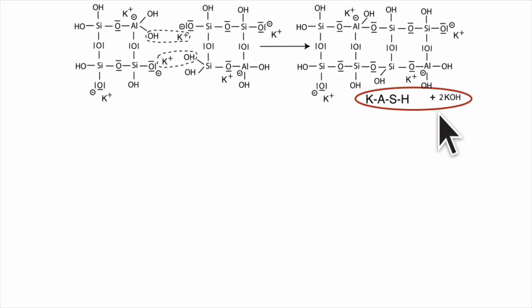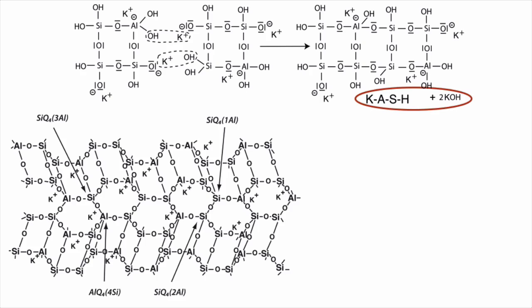So it is the potassium aluminosilicate hydrate. But it is the first step of geopolymerization. It is not the end result, because it continues to build the three-dimensional network. If you stop here, of course you have KASH. You have something that has 1 MPa strength; put it in water, it will dissolve, be destroyed. But this is not what we are doing. We continue polymerization, and we create a three-dimensional network.